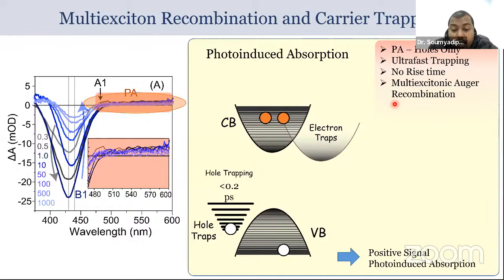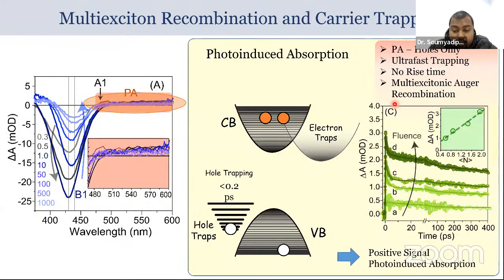Now, the thing is that when people say that the hole is occupied or something, this is not the movement of the hole, maybe the movement of the electron. Basically, what happens is the hole is in the lowest energy level. The other electrons are at the high energy level. So they go to the hole and the hole moves down. This gives a positive signal, which also can be found through fluence dependence kinetics.